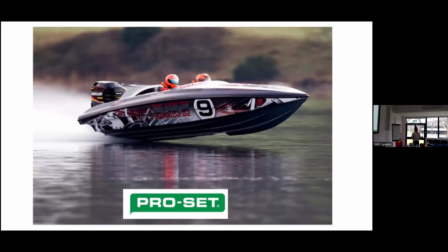You find that Olympic classes or dinghy classes that have adopted epoxy have a long, long lifespan, as opposed to a polyester boat that suffers from the micro cracking, because the polyester resin hasn't got as good elongation as the epoxy. That's not to say that all those 95% of boats that are built in polyester are no good. They're fantastic. They're production boats, sometimes built around the price, but generally fit for purpose.